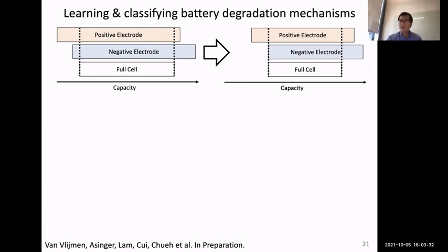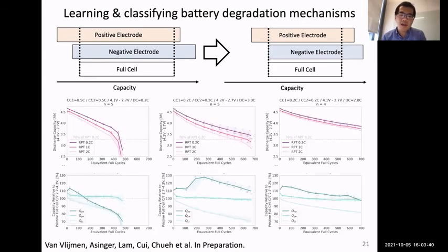So we incorporated this extremely simple physics-based model just based on the conservation of lithium, and we're able to apply this to our data set. And we can now not only extract the degradation in performance, we're also able to extract the degradation modes.